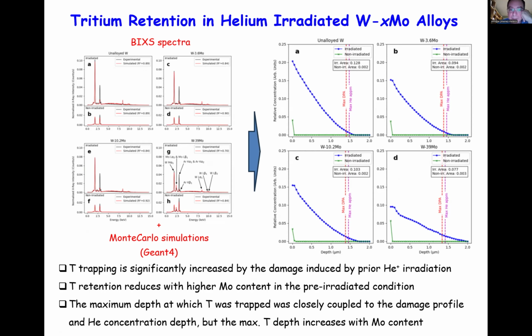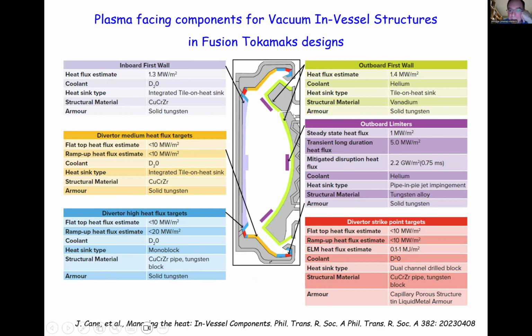that alloying element. Now, this is just to show you a cross-section of what I showed you before of the tokamak, where the plasma will be in the middle, just to show you that different components in the plasma-facing materials, or in the first wall, will have different conditions. You still will have tungsten and copper, chromium, zirconium, but the heat flux or the coolant are very specific. So we need to understand the local environments even within the first wall of the tokamak.